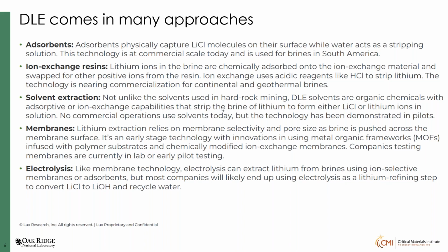And the other method is solvent extraction, where you use organic chemicals, the ligands, to selectively extract lithium from either chloride or even sulfate solutions. We don't have commercial operations as of today, but we know in the case of rare earth extraction, solvent extraction is the technique people use. It has already been used on a large scale for rare earth separation. Here at Oak Ridge, we have developed some work on lithium extraction using solvent extraction. My feeling is that maybe it's not for direct lithium extraction, but once you separate lithium chloride, solvent extraction may work for purification and concentration.